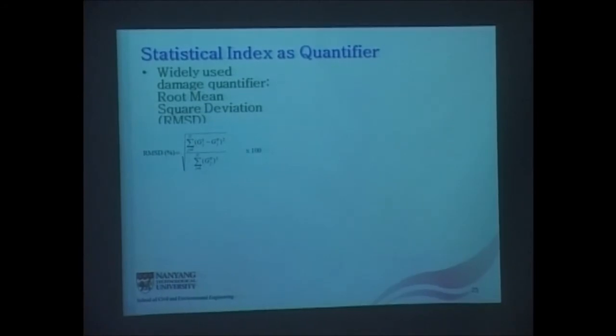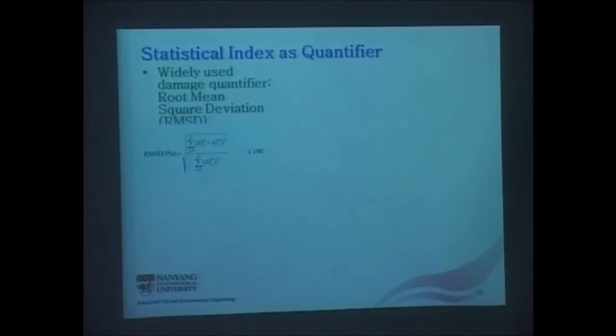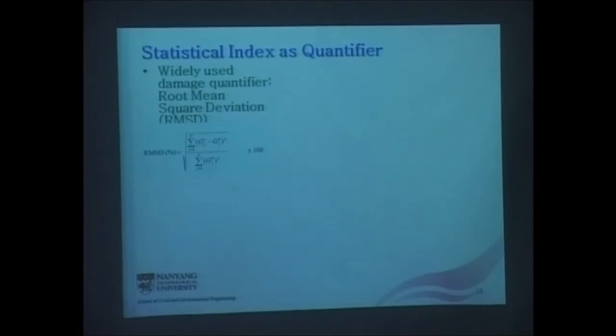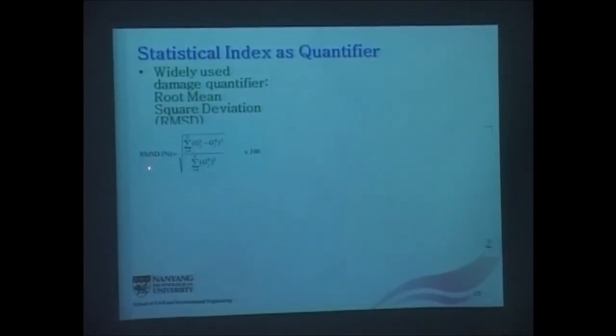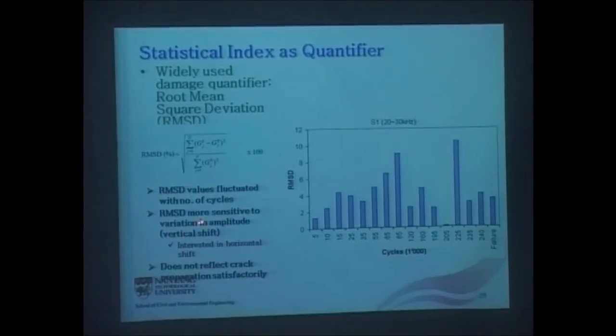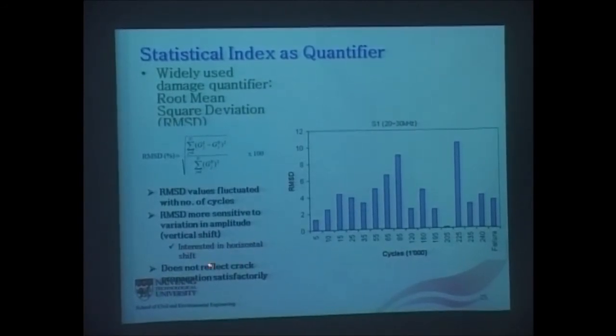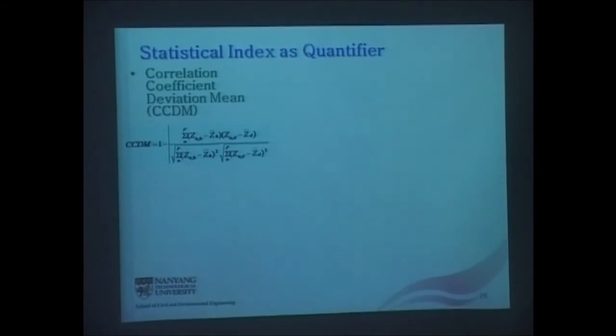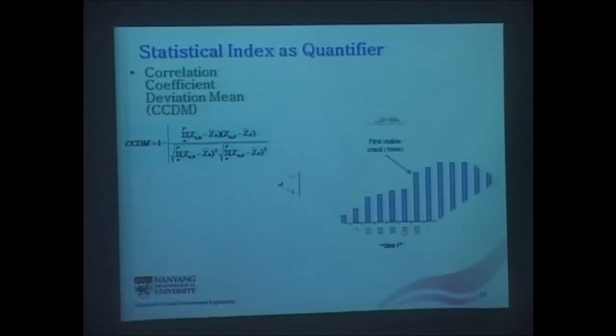The other one is the quantifier. Quite widely used is the RMSD method, which we found is not very suitable for this case because RMSD is good for vertical shift, while ours are more horizontal. And then we went on to another method.